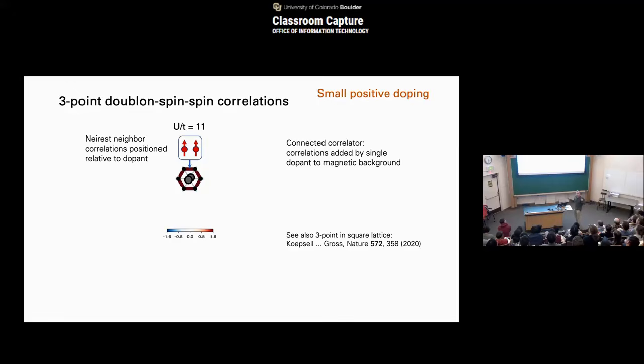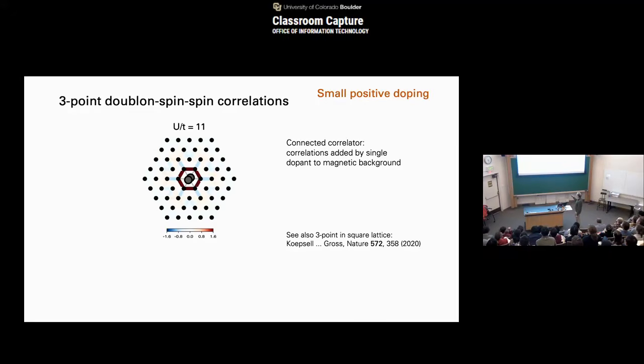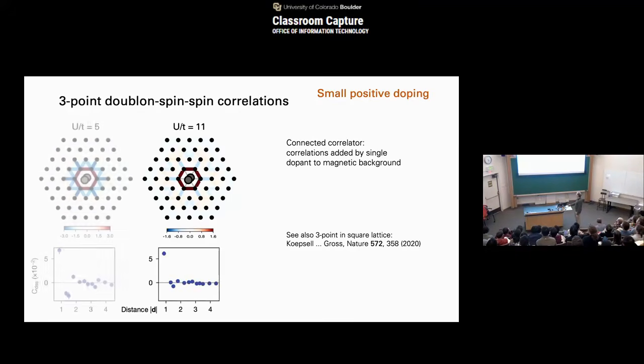Is this already Nagaoka magnetism? Well, the interaction is quite strong. You would actually expect Nagaoka to happen at higher interaction strengths. And in fact, yes, one has to be a little careful, because if you then look at correlations further away, they are still zero. So this only has a very local effect. And if you reduce the interaction further here, then we even get an oscillating behavior, even in this kind of metallic phase. So it turns out this is actually more like a Friedel oscillation. And so this isn't really Nagaoka. For Nagaoka, we expect this to have a longer range effect.